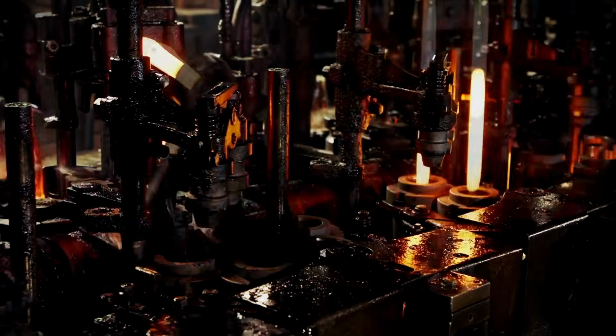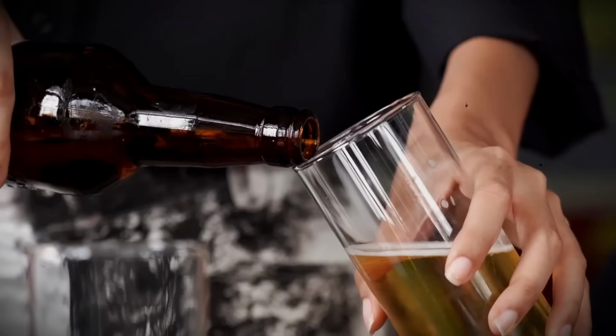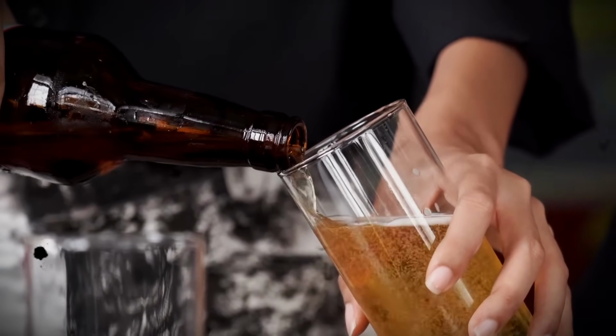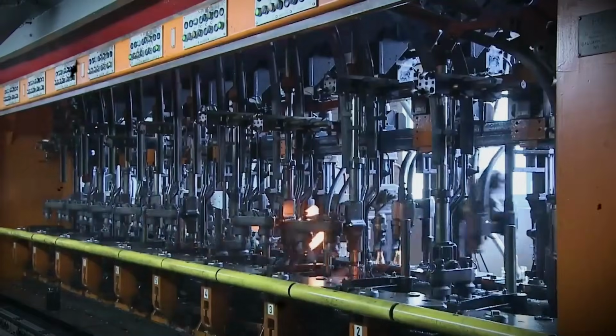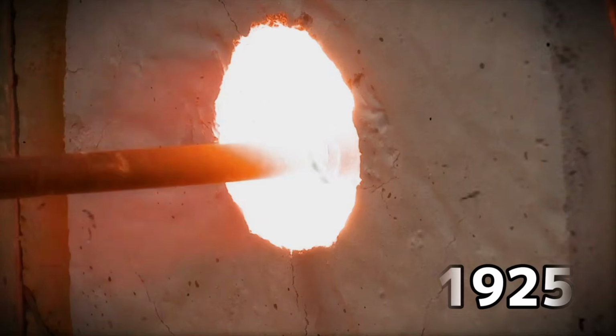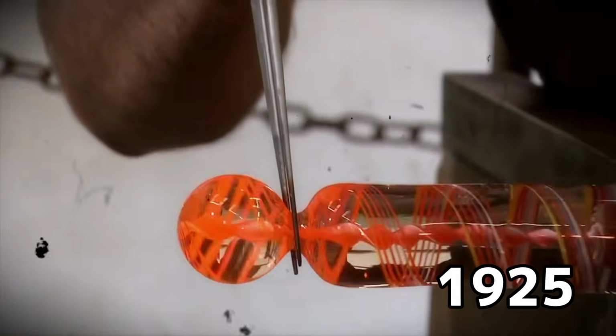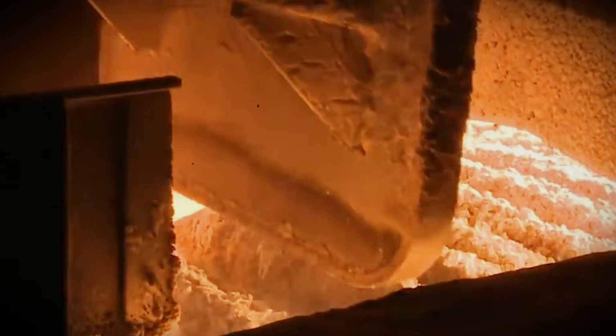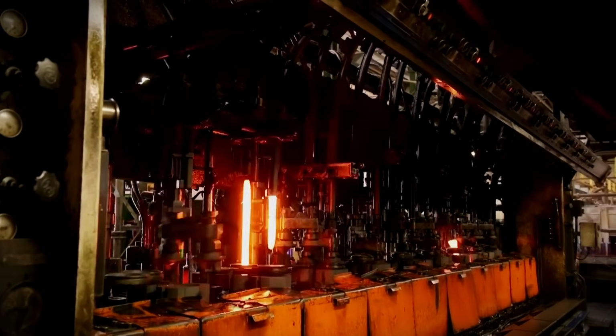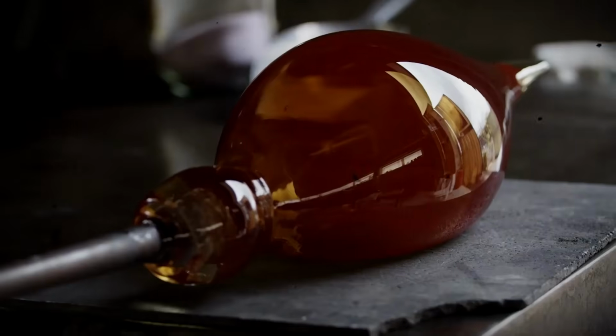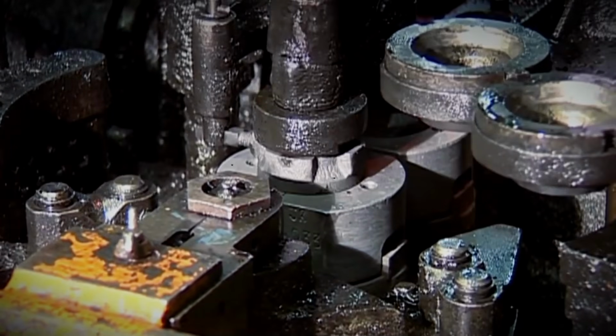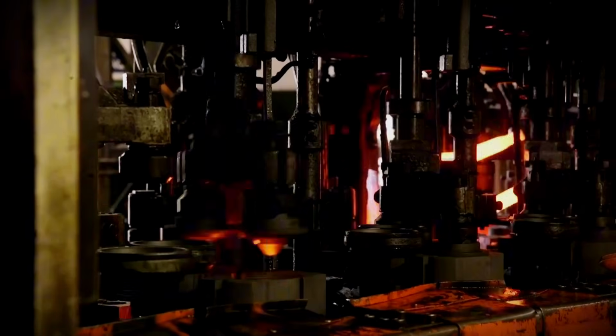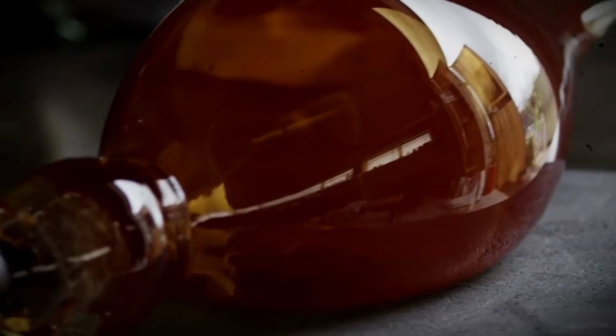But bottles and jars follow a completely different process. This is where the IS machine comes in, standing for individual section machine. Invented in 1925, it's still the backbone of container glass production worldwide. Molten glass flows into a feeder bowl where rotating orifice rings cut the stream into precise portions called gobs. Each gob is sheared by pneumatic scissors with split-second timing, weights controlled to within 1 gram. A typical line has 10 or 12 individual sections, each making up to 4 containers simultaneously.